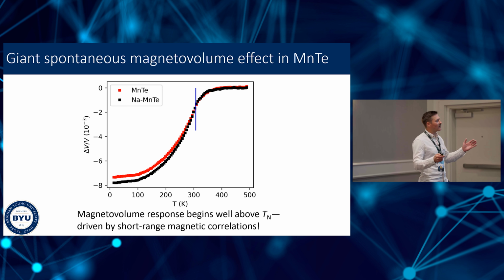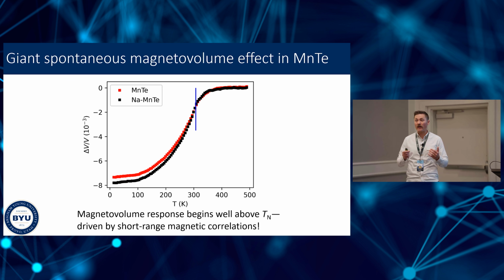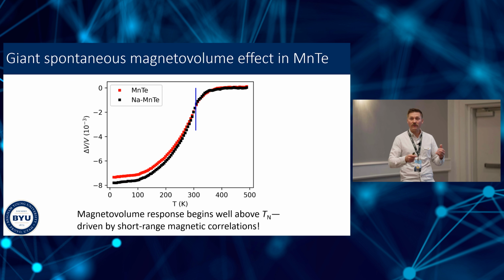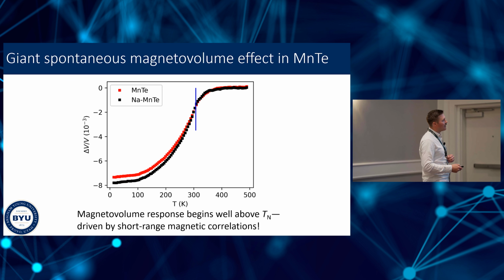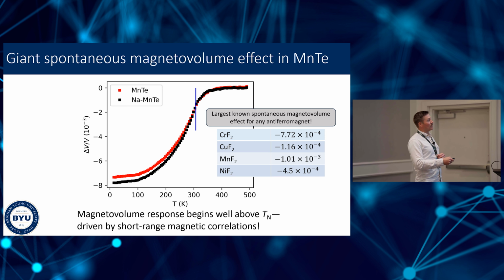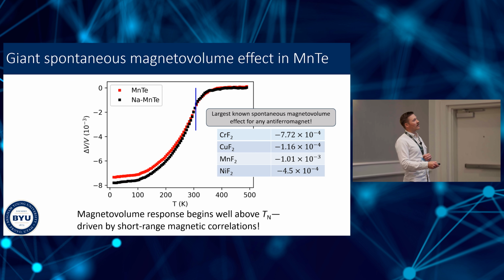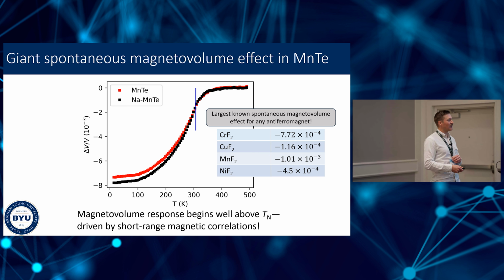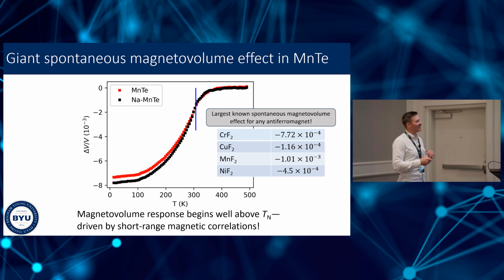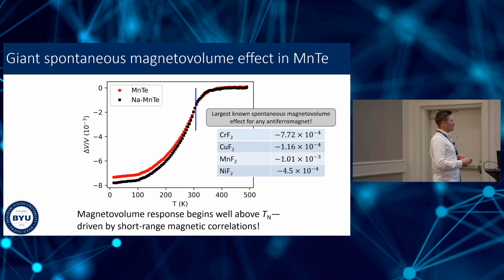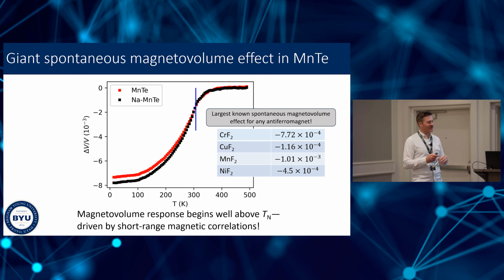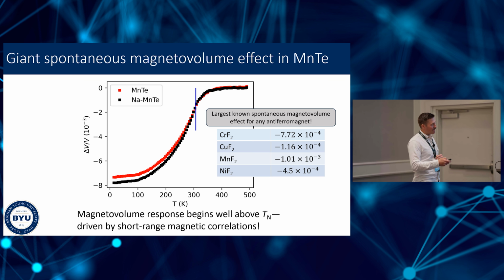Okay, so this is direct evidence that the short-range magnetic correlations are driving this macroscopic property, the unit cell volume, which is pretty cool. By the way, this happens to be an extremely large magnetovolume effect. This is almost 1%, okay? It's negative 8 times 10 to the minus 3. Other classic antiferromagnetic magnetostructural materials are an order of magnitude or more smaller, generally speaking. Okay, so manganese telluride happens to have the largest known spontaneous magnetovolume effect for any antiferromagnet, which was cool. We just stumbled across that.